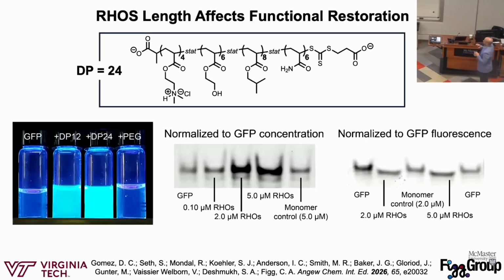We also ran some native electrophoresis. So what we're doing here is, because it's GFP and we aren't denaturing it, we're imaging the fluorescence of the GFP in the gel. So we can excite GFP and measure fluorescence on our gel scanner. If we look at GFP in this native gel, as we increase the concentration of our random heteroligomer, all of these lanes have the same amount of GFP in them, we're just changing the amount of rho. You see that the band gets darker and darker, meaning that we're increasing the fluorescence of that protein in this native electrophoresis experiment. This is cool because it means that these complexes are stable under electrophoretic conditions, which also suggests that they are actually interacting with the protein surface and they're relatively stable.